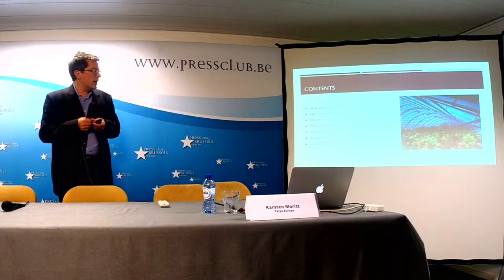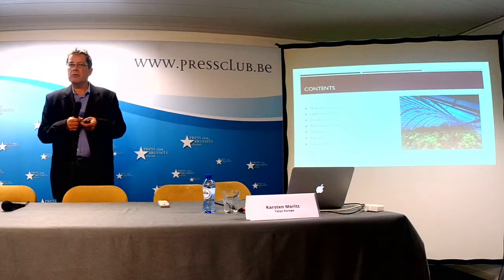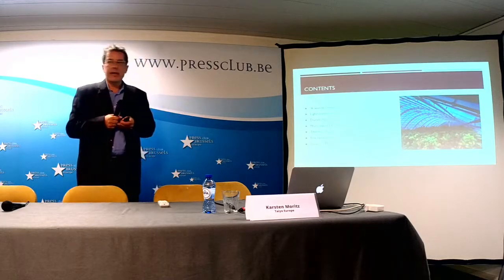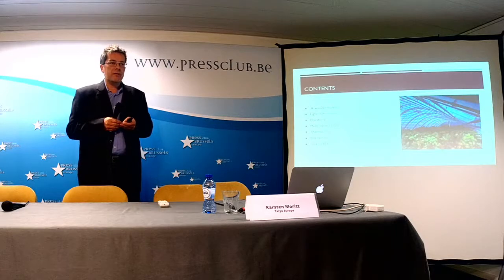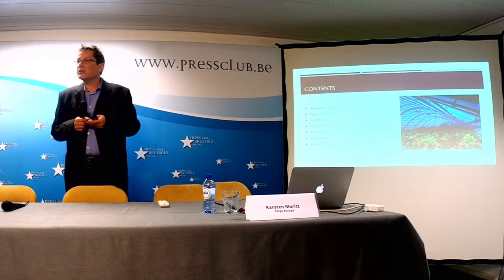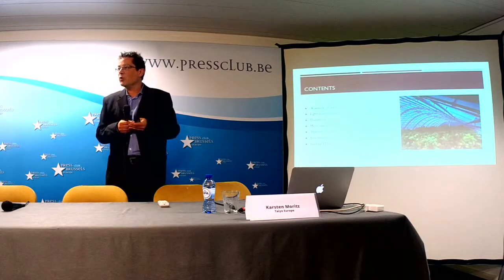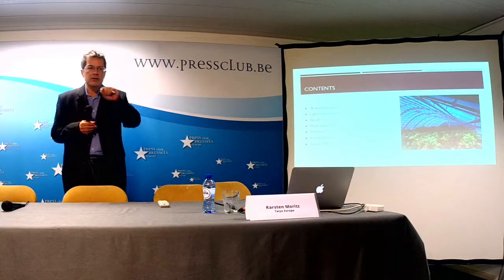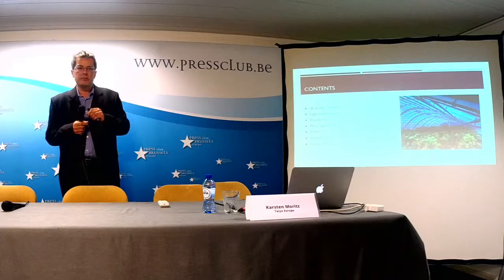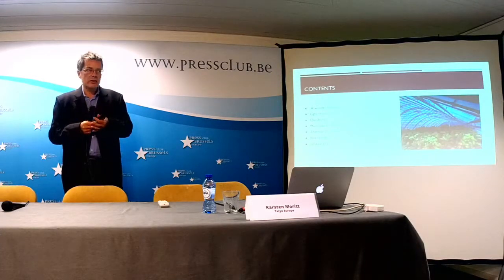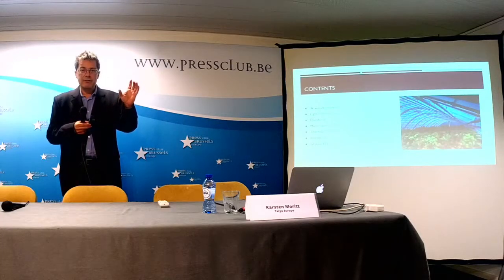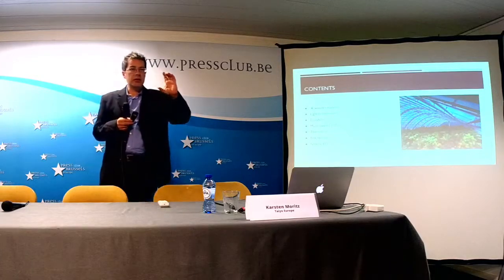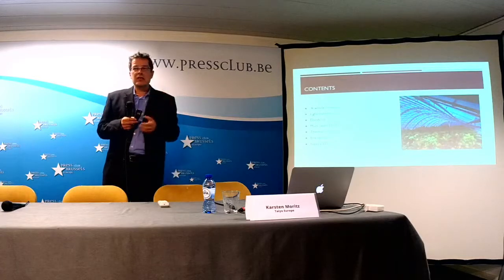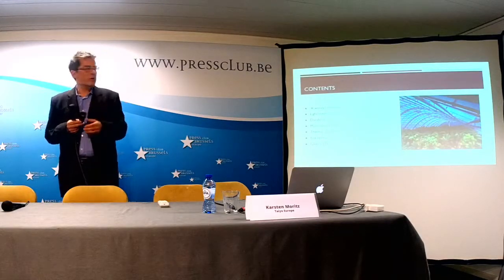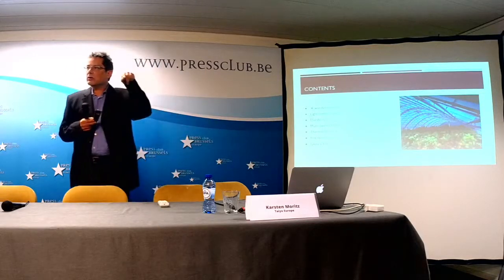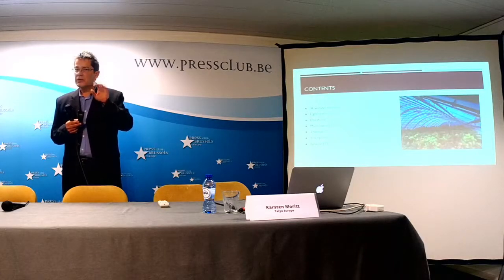There was a story behind this building. Let's say 10 days before the commissioning date, when we handed over this project to the client, there was a big hailstorm exactly above this location. And this hailstorm damaged the outer foil of these foil cushions. Many hundreds of holes were in the foils because it's a very thin film, 0.2 or 0.25 millimeters only, 250 micron. You can imagine that a hailstone with a diameter of 75 millimeters, these stones were so big, with sharp-edged surfaces, damaged the foils. Many holes in the outer layer. But the other 2 layers were still intact, were okay. Only the outer layer was damaged.